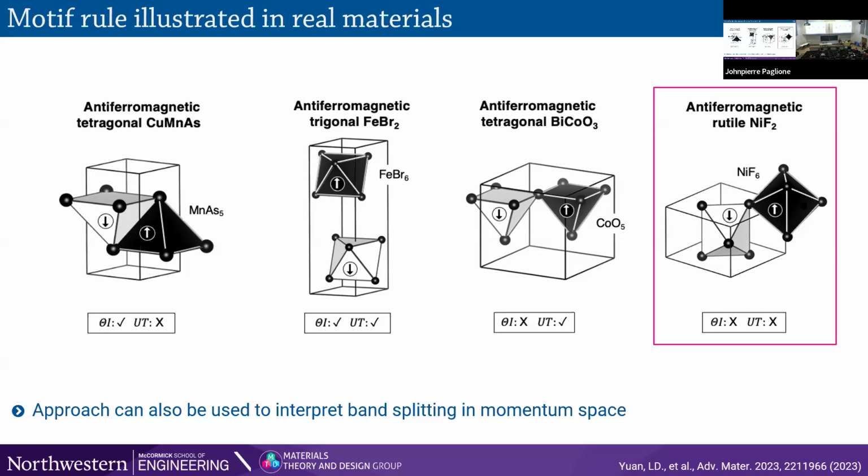Raphael? Very nice talk. It's very nice that you can do everything in this systematic and intentional way. But at the same time, how much can our reliance on the methods that we have limit us? Let me give you an example, like ruthenium oxide that I mentioned. People did first principles, and then they said, well, we have to do DFT plus U. If you do U of 1 eV, it's not, but 1.5 is. And then you start arguments like, well, 1.5 is much larger than 1, it's ridiculously large. We go to methods that we know don't capture it, try an approximation, and start overreading them. It's not a criticism of the method, it is what we have in hand, but how much do we need to improve methods or rely on multiple methods to constrain and view things?